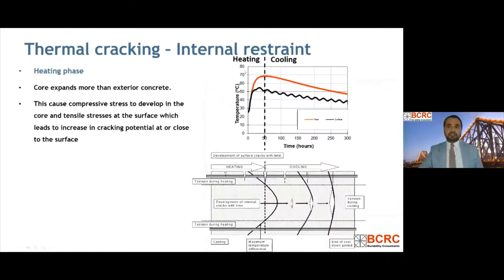If you look at this diagram here, in the heating phase, you see the temperature is going up. What happens is that the core expands more than the exterior concrete because it is much hotter. So when it expands more than the exterior concrete, the stresses in that core will be compressive stresses at all times, whereas near the surface you get tensile stresses, and that's why at this stage you have a lot of risk of having surface cracks.